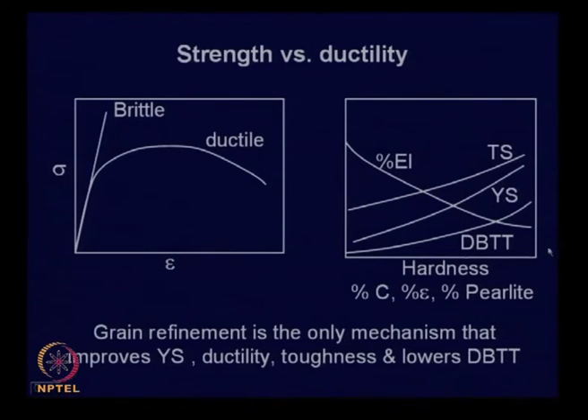And there is also another term we talked about, the ductile to brittle transition temperature, which is quite important for structural steel. Many structures are made of thick plates, particularly ships which go into regions of the sea where it is cold, and one of the main fabrication techniques for these plates is welding. When you weld thick plates, you have to make sure that welding does not deteriorate the properties in the welded region, and you do not increase the strength and adversely affect the toughness of the material.